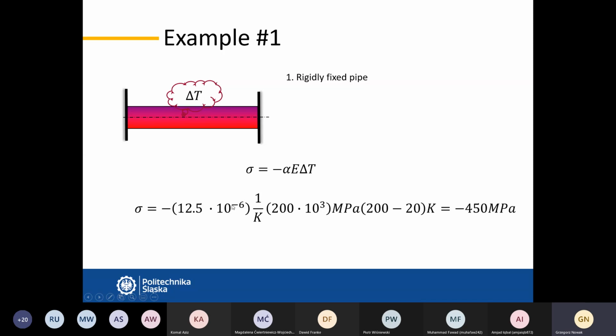So if we put the data in, we have 12.5 times 10 to the minus 6 power, 1 over K, 200 gigapascal, so it is 200 times 10 to the third power megapascal. And the temperature rise, 200 minus 20 in Kelvin. Kelvins cancel out, the result will be in megapascal, and we obtain minus 450 megapascal.